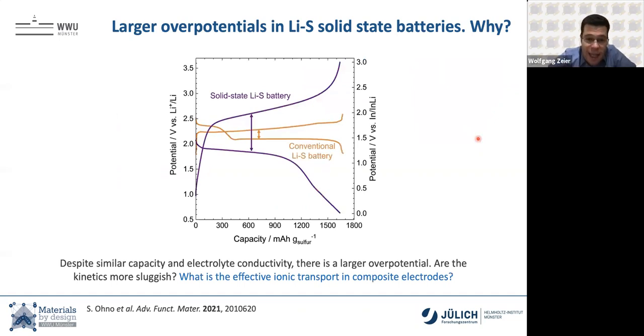Well, let's look at a charge-discharge curve, and I don't usually show a lot of those, so bear with me, of a lithium-sulfur solid-state battery in purple, directly compared to a conventional one that is in liquid electrolytes. And you see that the capacities, or the amount of charge you can put in reversibly and get back out, is very similar for both cell types, irrespective if we use a solid electrolyte or a liquid electrolyte. But the overpotential between these curves, so in the end, the resistance that we have between our electrodes, is much worse in the case of the solid state battery. Are the kinetics just more sluggish? I don't know. So we really need to look at what ion transport actually means if we think in terms of a composite electrode.